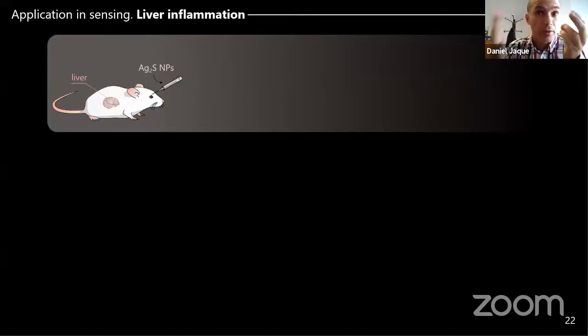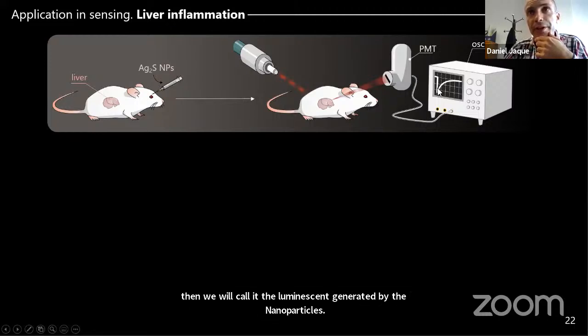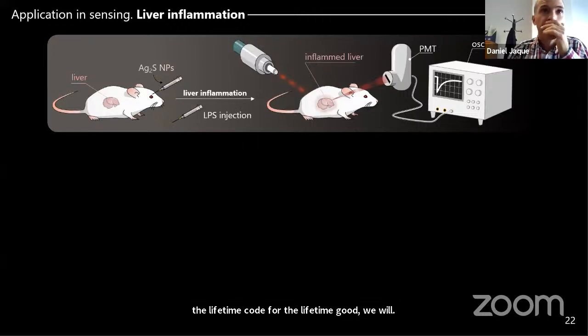We have tried here because we have a bright nanoparticle. So even if the nanoparticles are in the liver, we can get the light out of the liver, okay? So the idea is the following: we inject nanoparticles, and then the nanoparticles will accumulate in the liver. Then we will excite the animal with a pulse laser, and then we will collect the luminescence generated by the nanoparticles, and by looking at the oscilloscope, we are going to register the lifetime curve. And from the lifetime curve, we will estimate the temperature of the liver, okay?